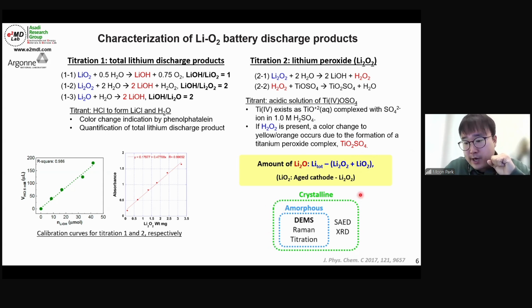So, the summary of the characterization for lithium-oxygen battery lithium discharge products: even though it is amorphous, DEMS, Raman, and titration can detect the lithium superoxide and distinguish it from others. And only in case the discharge product has crystallinity, we can use electron diffraction and X-ray diffraction.